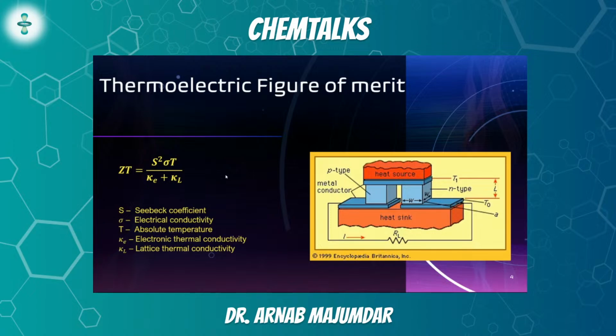So in order to increase ZT, just by looking at the equation, looking at the numerator, I can see that, oh, we could increase the S, the sigma, and the T. Or conversely, we can even decrease the kappa E or the kappa L, which is in the denominator. Sounds simple as well, but the problem is that these parameters are not completely independent. They are somewhat coupled. To give you an example, if we increase S, the Seebeck coefficient, my sigma tends to decrease. That means I'm not able to increase both of them simultaneously. At the same time, if I'm increasing sigma, my kappa E also increases, because sigma and kappa E are related by something called the Wiedemann-Franz law. And kappa E is something that we want to be low. We don't want the denominator to be large in value.